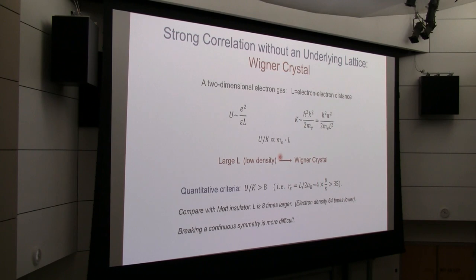So what you can see is, in order to get a strong correlation with a lattice like a Mott, you need U over K larger than 1. If you want to push it further, and you get U over K larger than 8, so that means if a lattice is 8 times larger, or density is like 64 times smaller, then you can even get a Wigner crystal. And the reason Wigner crystal is harder to get, at least for experimentalists, the hand-waving way to argue is a continuous symmetry. So it's a little bit harder to break compared with the one with lattice.